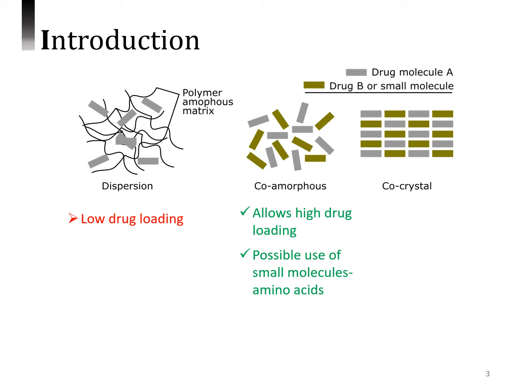Physical stabilization of amorphous solids revolves around two strategies. First, controlling the environment which can induce crystallization. For example, samples can be stored at low temperature or protected with appropriate packaging from moisture. Second strategy involves limiting molecular mobility of the molecules. This can be achieved by different techniques such as solid dispersion or co-amorphous systems.